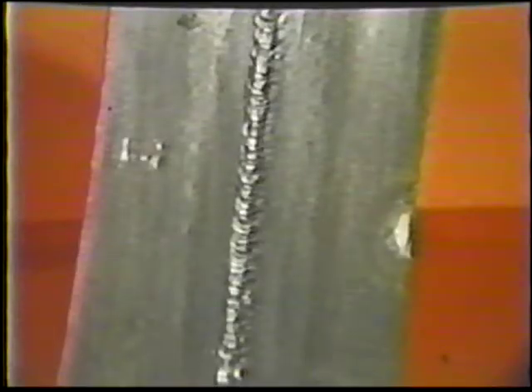The finished weld should be even, about 1/4 inch wide, and slightly convex. There is full fusion with both plates and full penetration to the root to form a slight reinforcement. Inspect the weld and continue practice.